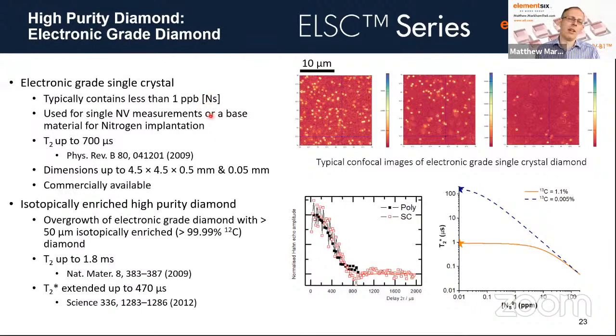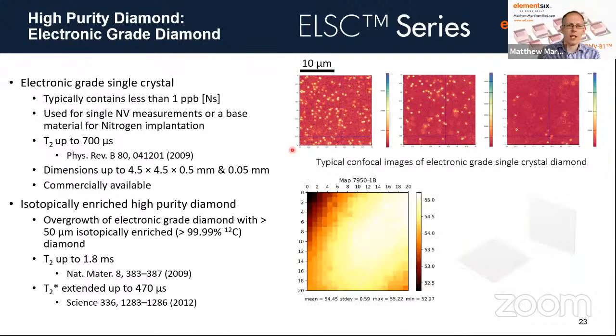and that corresponds to a much lower concentration of NV in this material, leading to these confocal images from Fedor Jelezko's group, where you can see the orange dots here are single NV defects in the material. And this material allows you to have T2s up to 700 microseconds. You can also do isotopically controlled versions of this. This is not yet a commercial material, but that obviously has a massive extension on the spin lifetime that you can achieve. And we've recently launched a mil thickness variant.